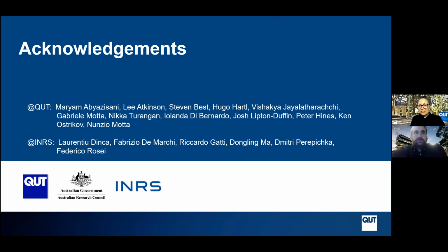I forgot to mention that. I should have shown a picture of the setup. Our system has XPS, which has both the X-ray and the ultraviolet source. It's an SPM, so we can do either STM or AFM on our scanning probe instrument. And we've also got our inverse photoemission spectrometer in there, as well as spot profile analyzing LEED. So we can do a range of things.